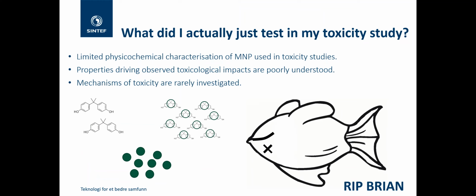So when we put all this together, the question is, for me as a chemist, I would always ask toxicologists, what is it that you actually just tested in your toxicity study? Because my experience from looking at the literature is that there's really limited physical chemical characterization of the test materials that are used in toxicity studies, particularly the chemical side. There's not been very much focus on the properties of the particles that are driving the observed toxicological impact. So I don't know whether it's a particulate effect, whether it's a chemical effect, and so on. And there's virtually no focus on looking into the mechanisms of toxicity.